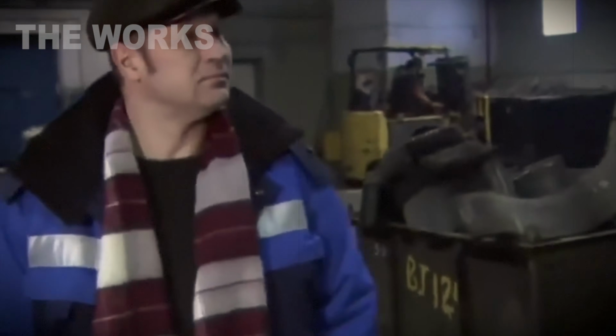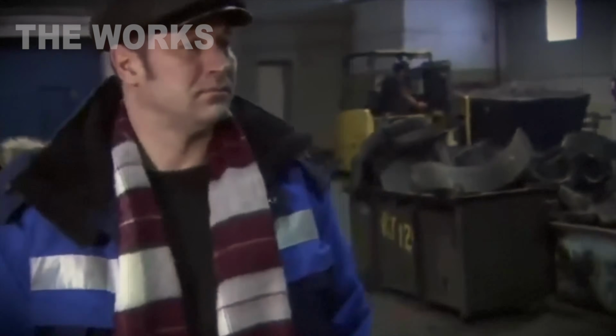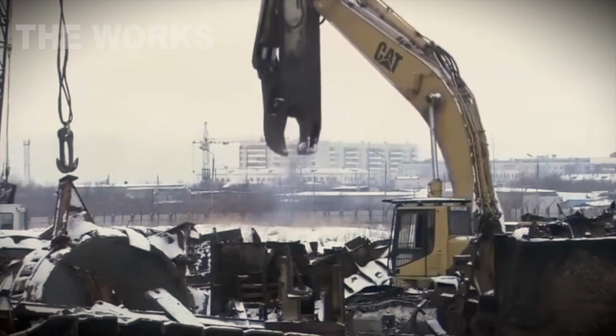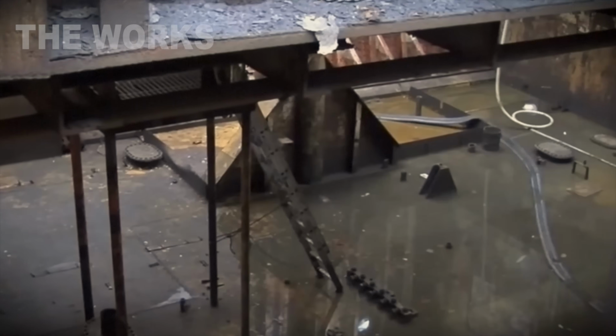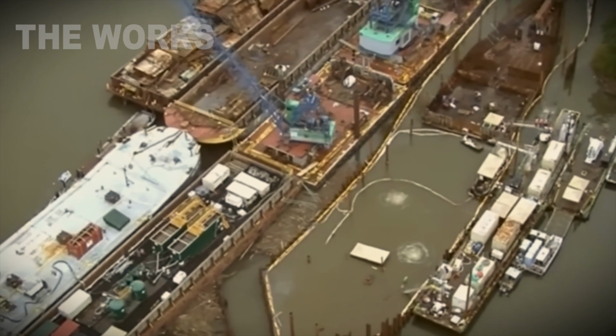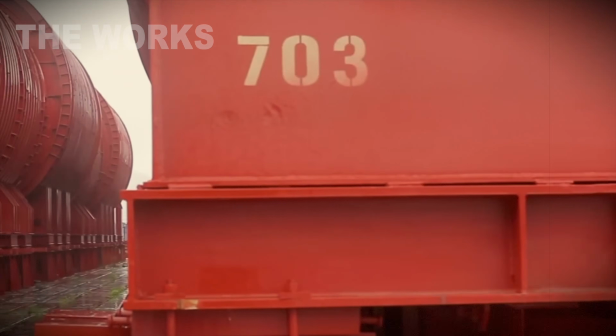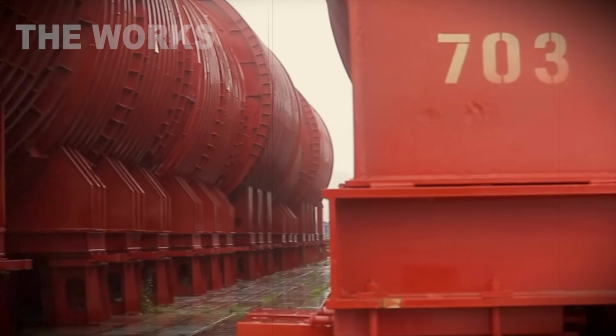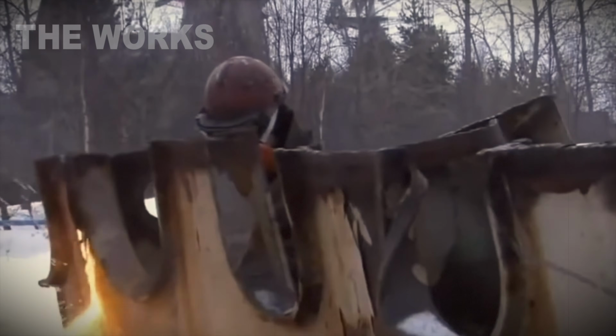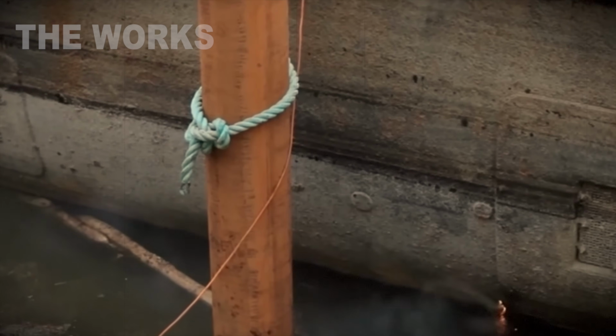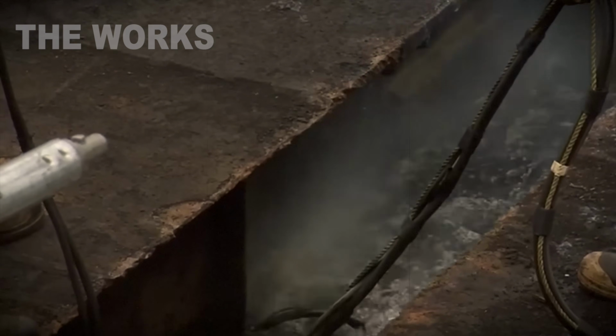Decontaminate with ultrasound. Frequency, 40 kilohertz. Power, 3 kilowatts. Ultrasound breaks down the oxide film. Then they rinse the plate with alkaline solution and dry it with hot air at 250 degrees. Only after thousands of air samples and surface swabs, when everything reads 0, they open the dock to regular workers. Now it's not a nuclear facility, it's just a complex steel structure.